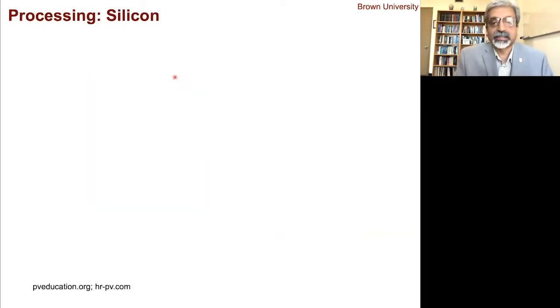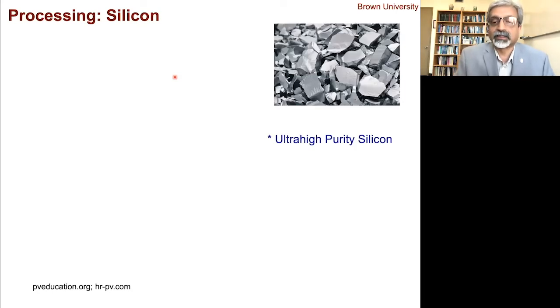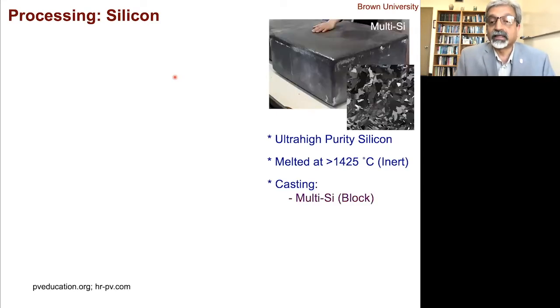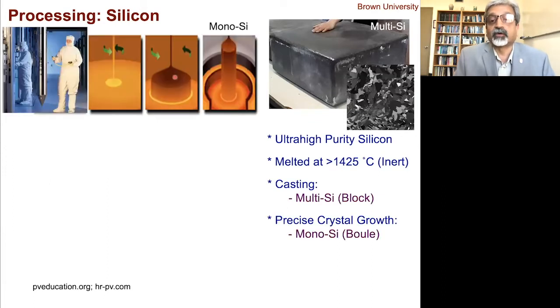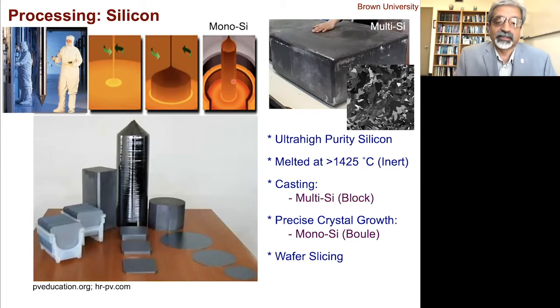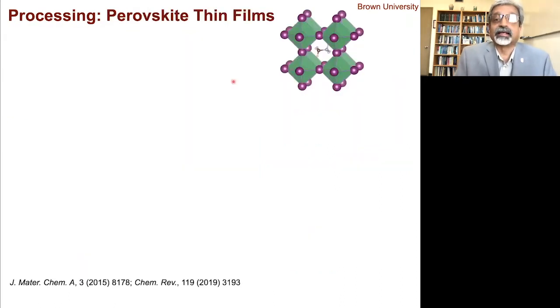Now let's talk about processing. So compare this with silicon. With silicon, you have to use ultra high purity material, which has to be melted at very high temperature, above 1425 degrees C, which is where silicon melts. For multi-silicon, you can cast it. For single crystal silicon, you have to grow this into a boule very carefully. This is actually a similar silicon that is used in your computer chips. So single crystal without any grain boundaries. And the wafers are sliced from this, and it takes about 5 tons of silicon to make a megawatt worth of silicon photovoltaics.